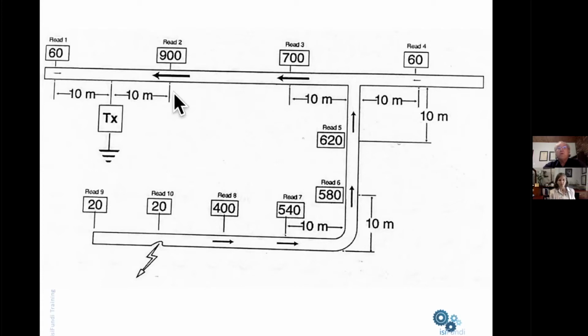And if we follow this pipeline route, if you were to go along here and assuming that you think that this pipeline just goes straight, well, yes, it goes straight, but when you get over here, you find that there's no current flow. Where's the current gone? So then you start scouting around and you can pick up the current at this point here. Or if you knew that there was a pipeline network, you can go and measure this just like you do using Kirchhoff's law in an electrical circuit. You know, current in equals current out. And therefore, you can say, well, my biggest issue now is actually on this branch. And if I follow the branch, you can use this to actually trace the branch.